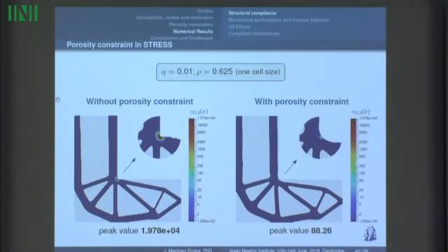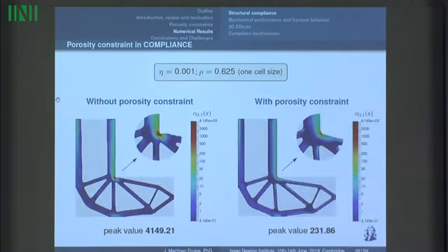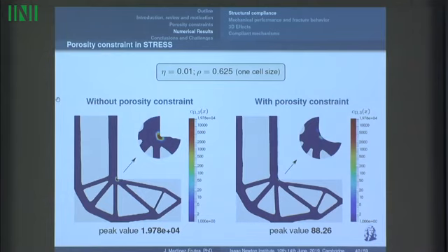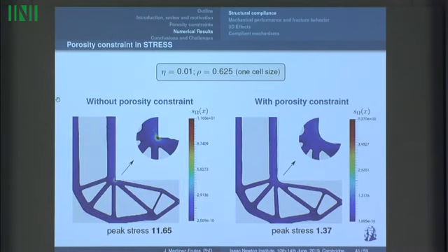So let's see what happens when we introduce the porosity constraint in stress. In this case, we have similar changes in the optimal shape. We see that the peak value is also reduced a great deal, and this topological optimal shape seems to be the same as this one. It is very, very similar, but we will see later on when we analyze fracture that it has slight differences. When we introduce this porosity constraint in stress, we also have some extra benefits: the stress level in the structure is also reduced, the peak stress from 11 to 1.3.